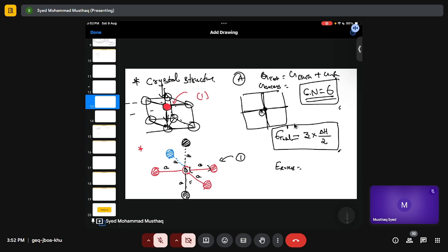So we can even call it ideal energy. Now, if I remove the bulk part and still find some energy, which is the surface energy, we call it excess energy. So we can write that excess energy as the number of bonds being broken times delta H upon 2. Right? So this is our excess part.